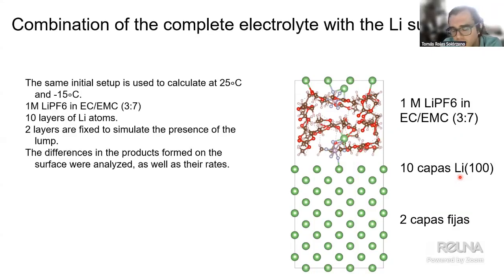But we cannot just infinitely produce layers of lithium in order to see the big chunk of material that is not going to react with the electrolyte. So what we do is that we fix the coordinates and we restrict the movement of those layers, to represent that we expect the electrolyte to work with the first 3-4 layers of the anode, but beyond there, it will be fixed and it won't be affected. But we are mostly interested in those 3, 4, 5 layers of interaction.